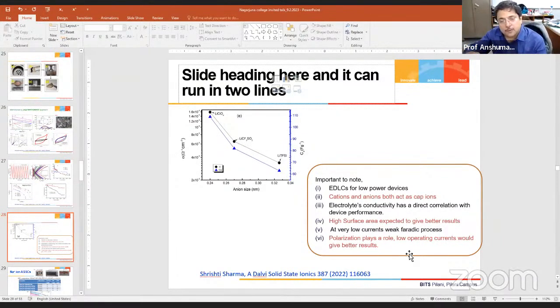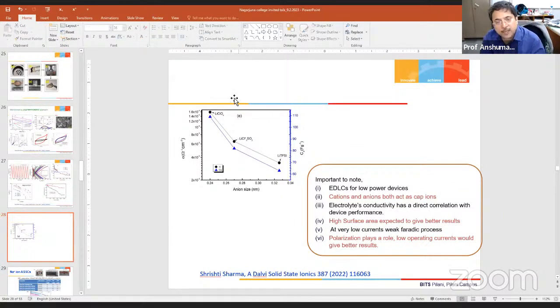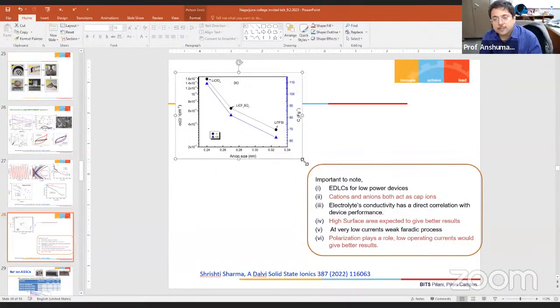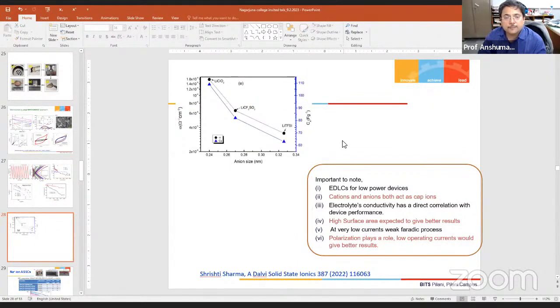In the batteries, you take a bigger anion. A bigger anion is going to help you because that will promote single ion electrical transport. A bigger ion will get stuck somewhere. But in supercapacitors, you have to choose a smaller ion. Of course, it should not chemically react and subject to other conditions. These anions, being smaller in nature, are showing better results. So we see that if you have lithium perchlorate, which has the smallest anion, it will perform better. It will show a good result.